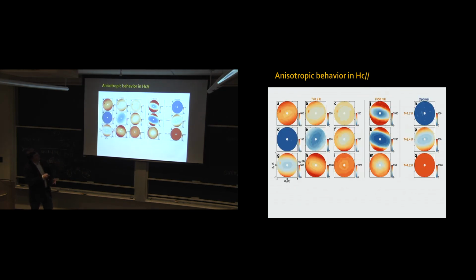It looks like this. And all of these things we can measure as a function of density and temperature - we have so many tuning knobs here compared to other systems, it's very rich. As you can see, this ellipse changes direction of the axis, which tells you this is not simply nematicity due to strain - it's something else going on, of electronic origin. This happens in many correlated materials and has deep implications for the type of superconductivity.